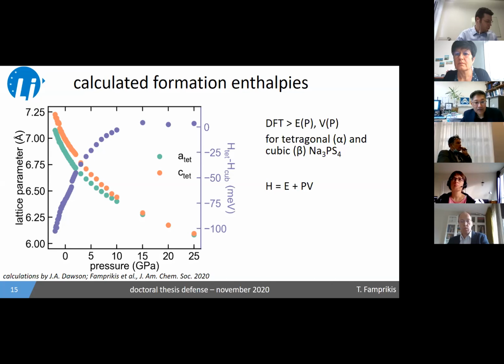And we can also calculate the enthalpy of formation of the two polymorphs. I'm plotting here in purple the difference between the enthalpy of formation of the tetragonal and the cubic samples. You can see at zero pressure, the value is negative, so the tetragonal polymorph is favored. But as we increase pressure, this difference, or the absolute difference, decreases to the point where at 15 gigapascal, we get something very close to zero. So basically, we have stabilized the cubic polymorph through pressure. So we can say that we can understand the effect of mechanochemistry on stabilizing the beta polymorph through the aspect of applying pressure to the material.